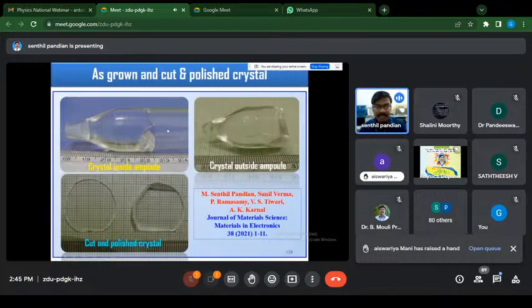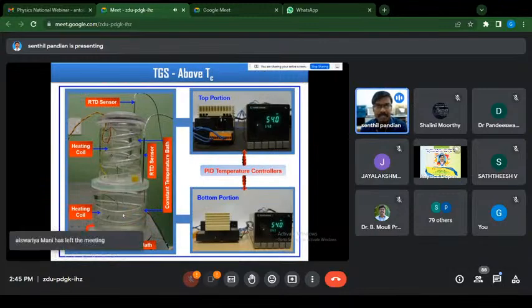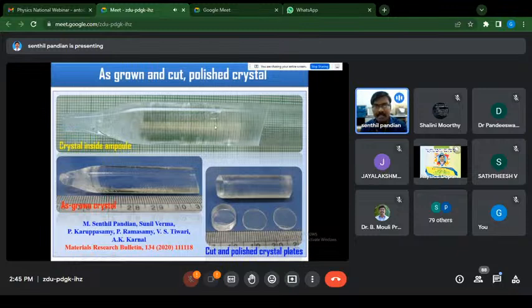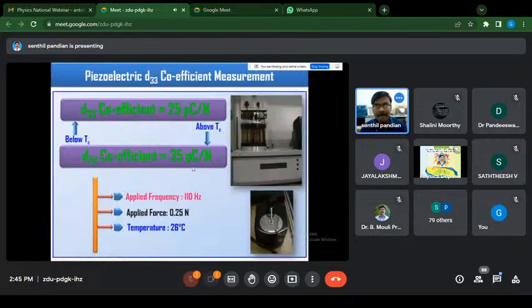So this is the ferroelectric faceted grown crystal, which we reported in 2021. And this is above TC. We maintained the temperature at 54 degrees Celsius at the top and bottom portions. And this is the paraelectric faceted grown TGS crystal. We compared the physical properties, chemical properties, and the crystalline perfection of the grown crystals.